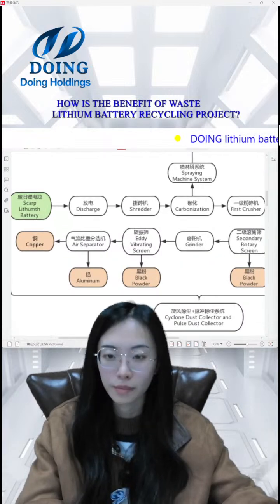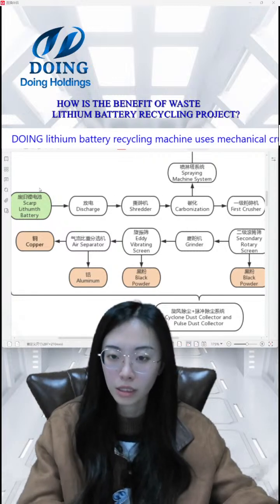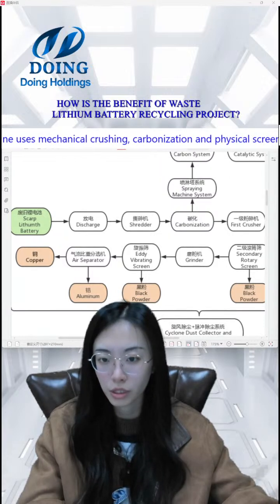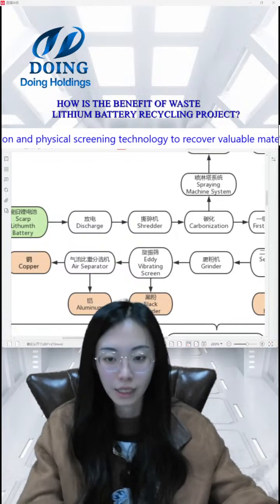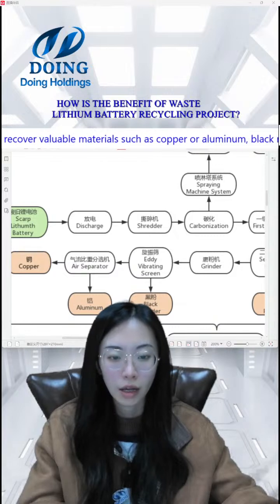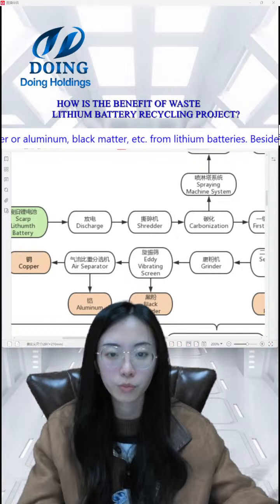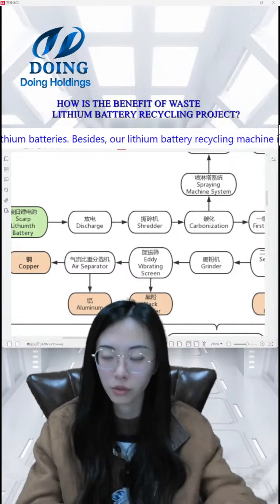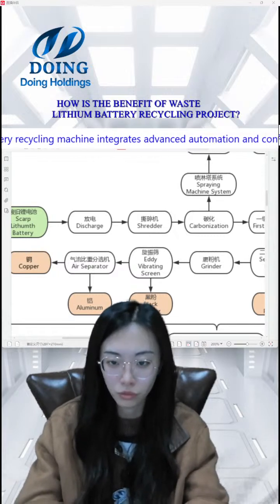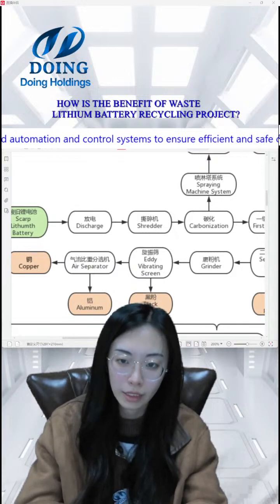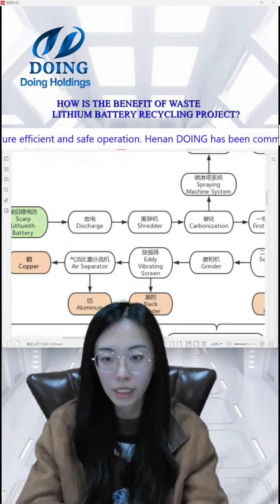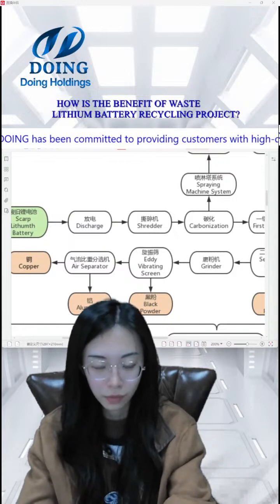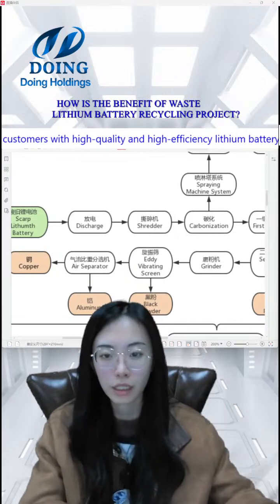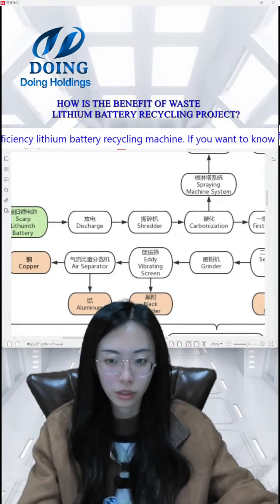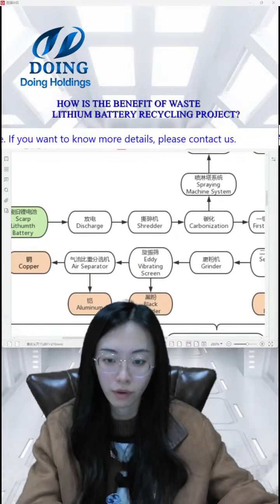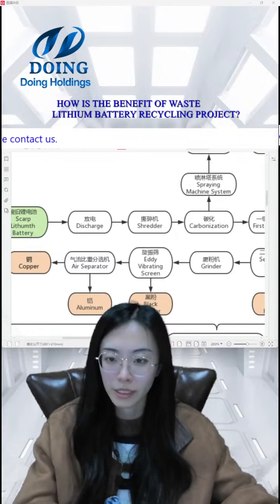This picture starts from here. We get the scrap lithium battery, and then we need the pre-process. The first one is to discharge it, because they have some electric power inside. So we first have the discharge process: we put the scrap lithium battery into a chloride solution with a concentration of 8 to 15%, and soak for 2 or 3 days to fully discharge the electricity inside, making the negative side and the positive side of the battery short circuit, to ensure that we can crush and separate the lithium battery in a safe environment. This is the first pre-process, discharging.